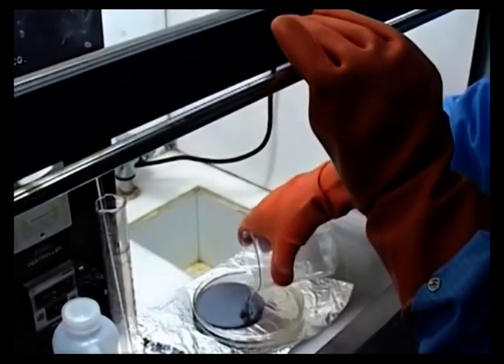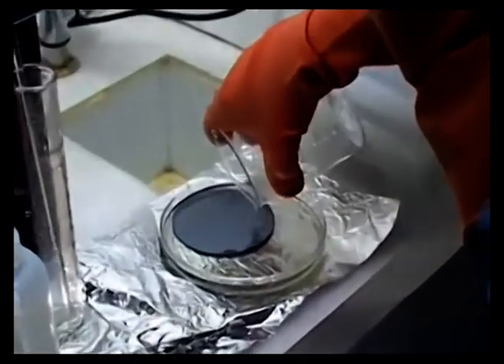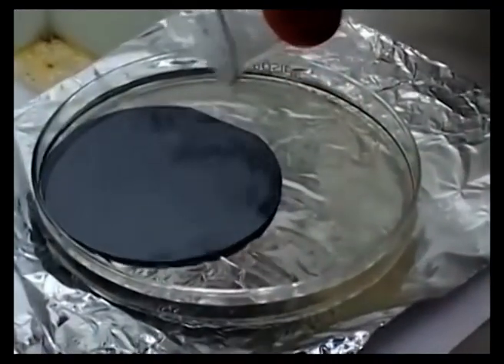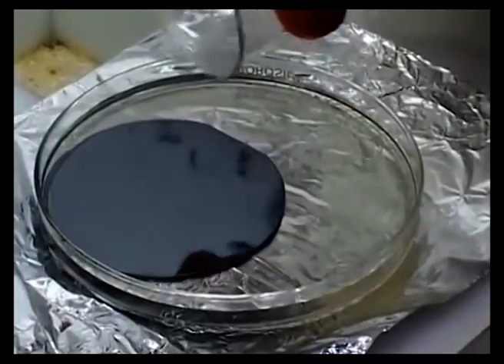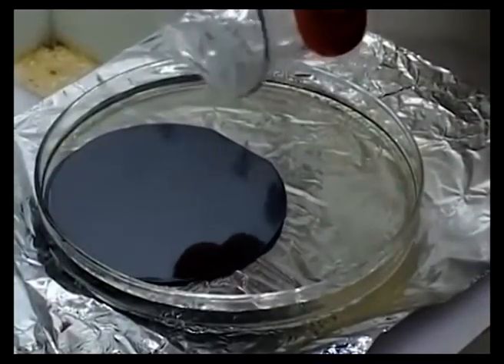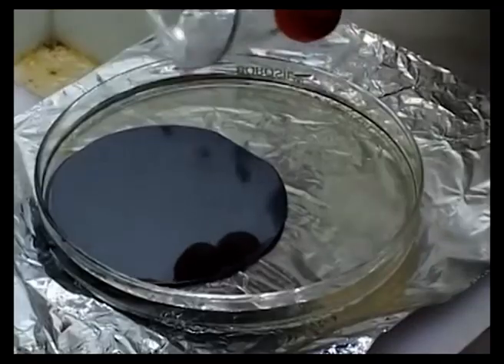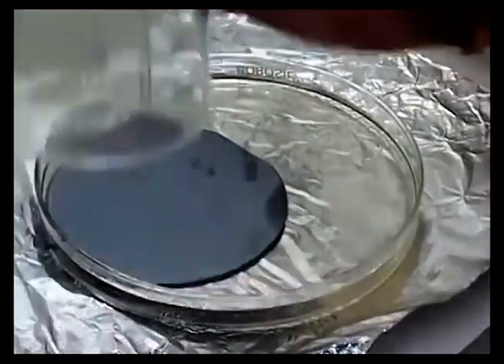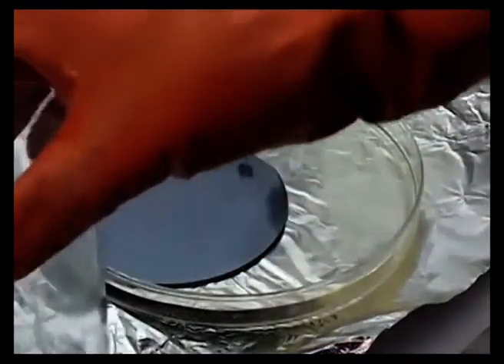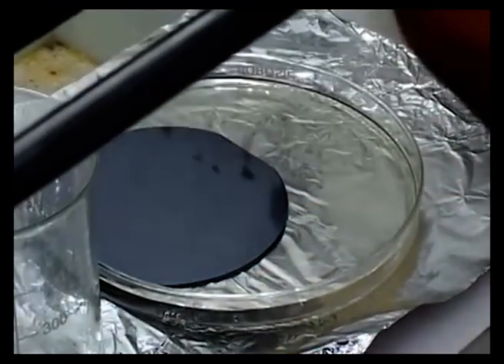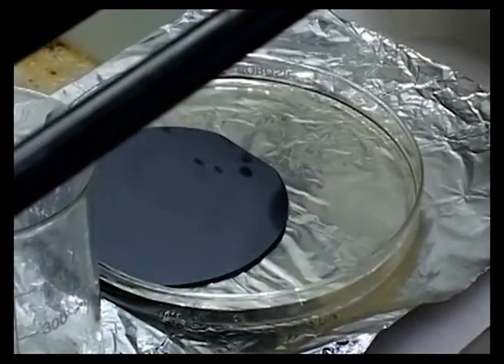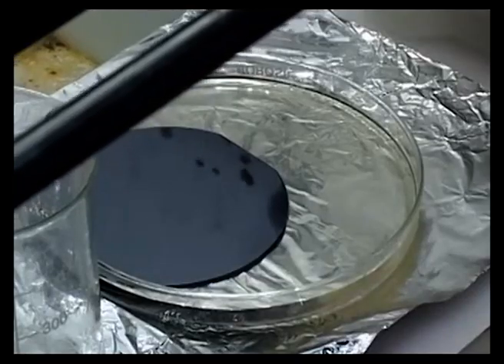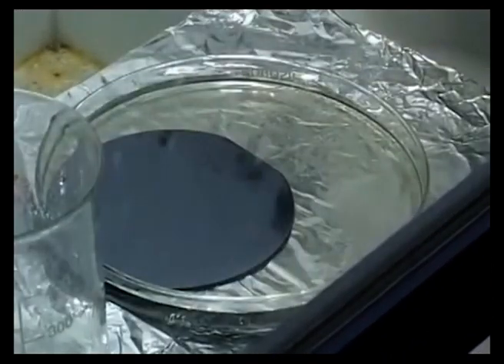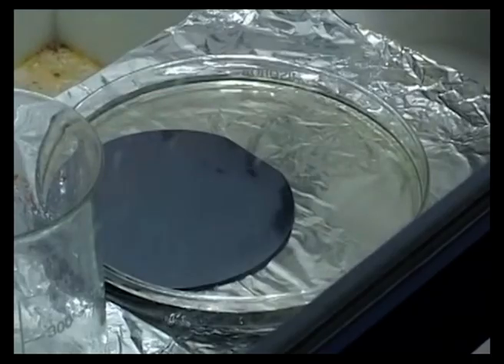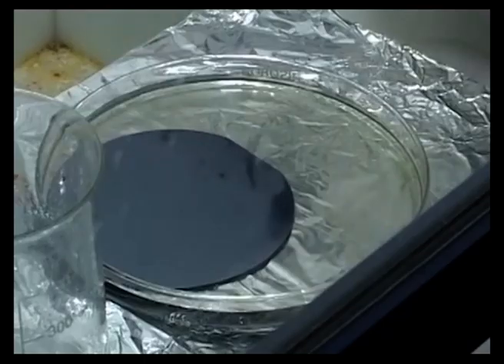it also fumes as you pour it, and immediately, if you can see, the organic contaminations over the silicon surface have been immediately removed, and we store all this container later on for cleaning and using it, okay, for different applications. So now we keep this closed and wait for about 10 to 15 minutes so that the wafer can totally get rinsed.